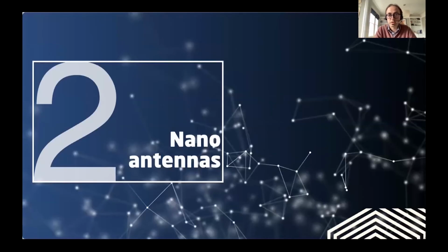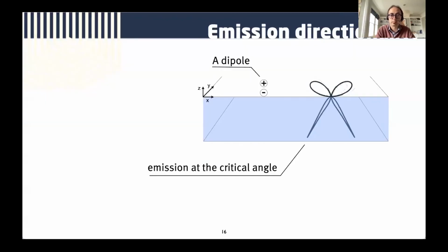So the second aspect that we need to understand how we can enhance the light is to think about nano antennas. Here, what I want is to use a nanostructured material as a way to connect the far field of propagating waves with the nanoscopic size of our emitter. The reason why I need to use an antenna is that if I take a dipole, and this works for any dipole, so this could be from a 2D material or from a single emitter, and I place it on a high index substrate, which is our typical substrate, which is here the blue part, then this emitter will emit light mostly inside the substrate at a very large angle, close to the critical angle, which are angles that typically are very hard to collect.